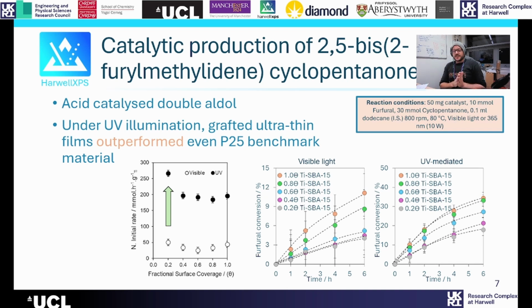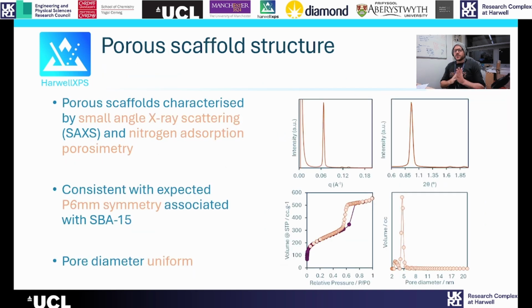When we normalized for titanium mass, most of the materials reported equal activity apart from one. Our lowest loading material reported a 25% increase in initial rate compared to the rest, and this was reflected in both the visible and the UV light exposed reactions. But why? So let's go back to the start. We need to understand our materials to discern why we observe this discrepancy.